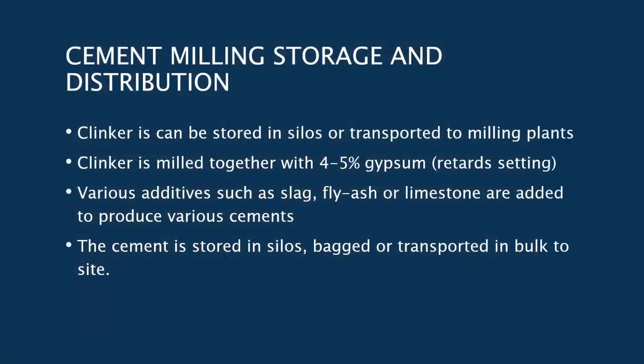Okay, your clinker can be stored and transported, and now they add 4 to 5% gypsum to it when they mill it, and this retards the setting. Otherwise, you often get flash setting in cement, and you can't really mix it. We now have a variety of additives that can be added to this, such as fly ash, limestone, and they're all extenders. They extend the volume of the cement.